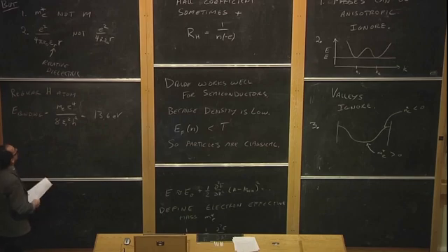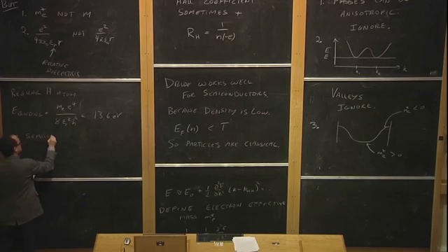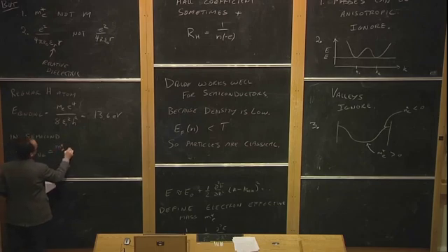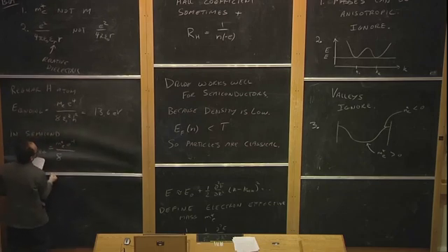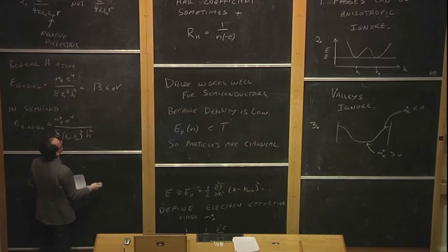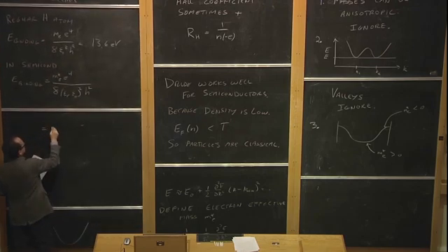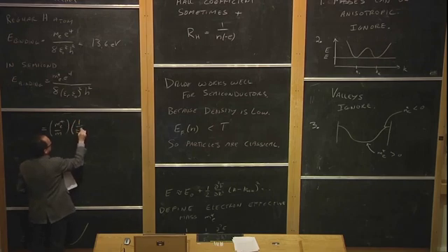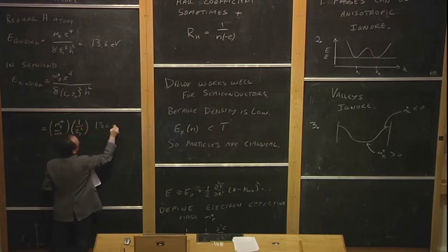So this is the binding energy of a regular hydrogen atom, but in a semiconductor, the binding energy, E binding, of the electron back to the proton, the additional charge that I put in with the dopant, is now m star electron e to the 4th over 8 epsilon relative epsilon naught squared over h squared, which I can then write as m star of the electron divided by the mass of the electron times 1 over epsilon relative squared times 13.6 eV.